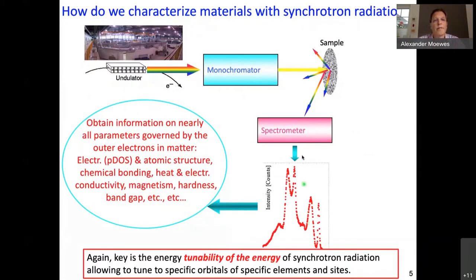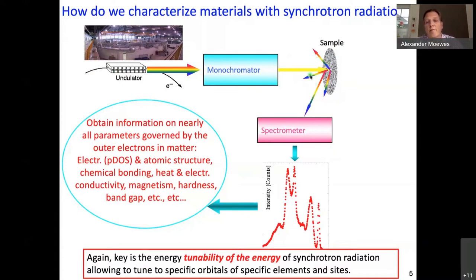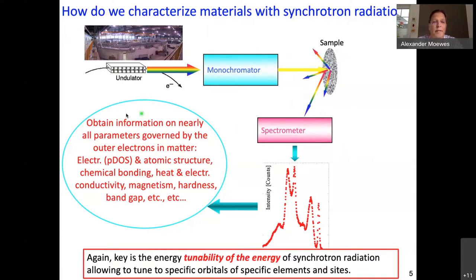How we do this is, of course, with the help of CLS. We have to use an undulator beamline at REIXS. We have a monochromator that selects the energy that we would like to have impinging on the sample. Of the multitude of processes that are happening, we focus on basically two: one is the absorbed photons, and the other one is the emitted photons that are monitored by a diffraction grating spectrometer. Our emission, absorption, and inelastic X-ray scattering spectra can then be related to all the properties I mentioned.